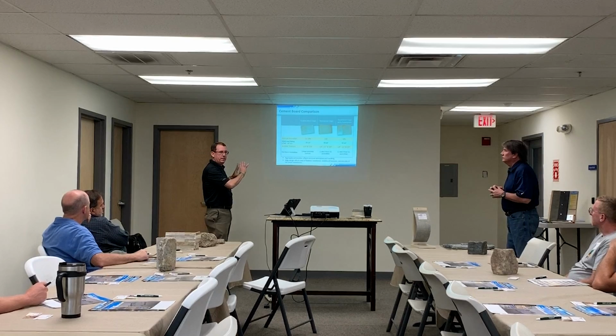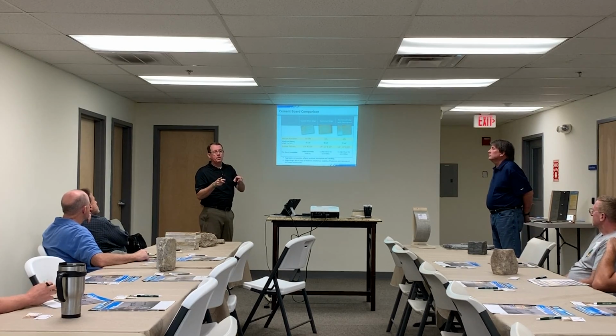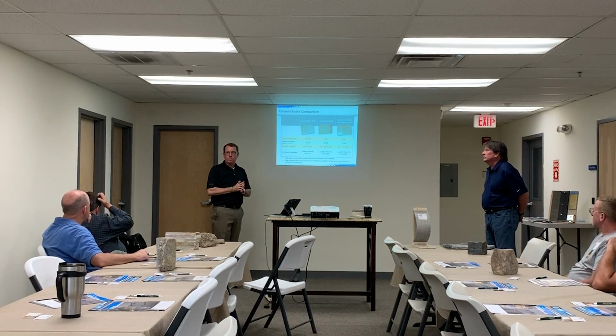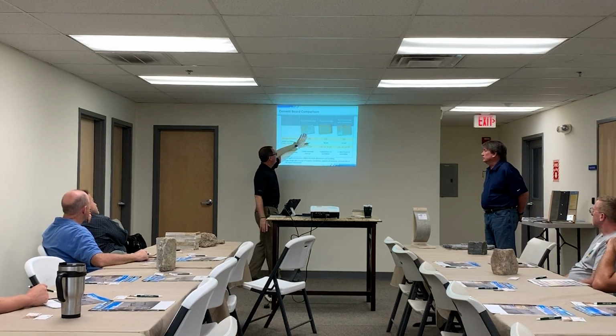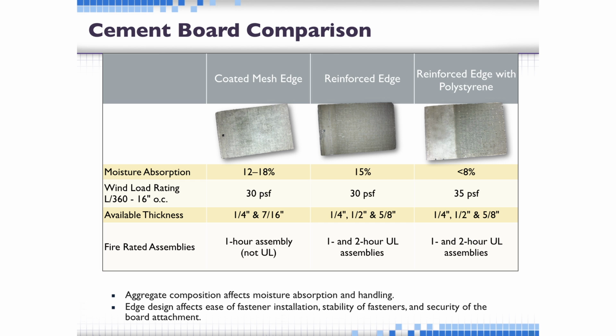That's key for two reasons. When you're setting tile with thin set, it doesn't suck all the moisture of the thin set into the boards really quick, number one. Number two, as we get into the exteriors, we're going to be applying an air and moisture barrier to our cement board before sticking stone, and we don't suck all of that into the board when you don't get the coverage rate. The air and moisture barrier is expensive. It's not a cheap 5-gallon bucket, so you want to make sure you get the coverage rates. When using these products, you're not going to get quite the same coverage rate as here.